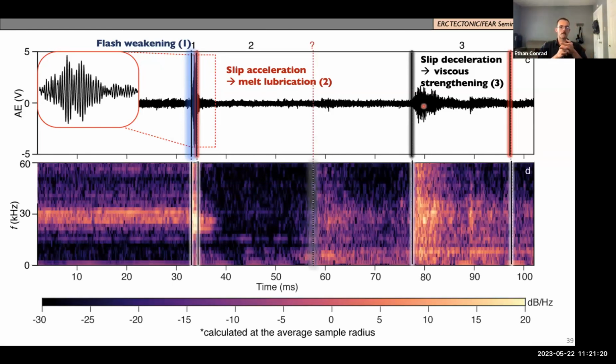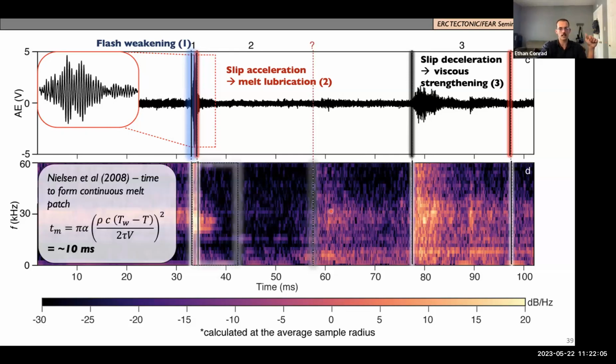Looking at a spectrogram from this time series, we see some precursory signals buried in here, and then you have the burst in AE power associated with the rupture, and then it's silence as the melt is formed, and that melt is attenuating the sound waves that are being emitted from the interface. There's this question mark period where we see a flash in power, and then we have the slip deceleration, viscous strengthening. So we're uncertain about this and what this actually represents. Maybe another mechanism coming into play, maybe just the gradual slowing of the interface, the gradual increase in melt, and therefore leading into that viscous strengthening.